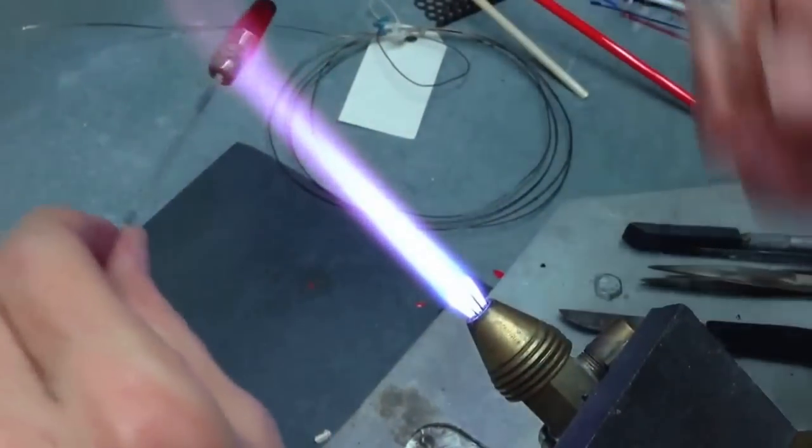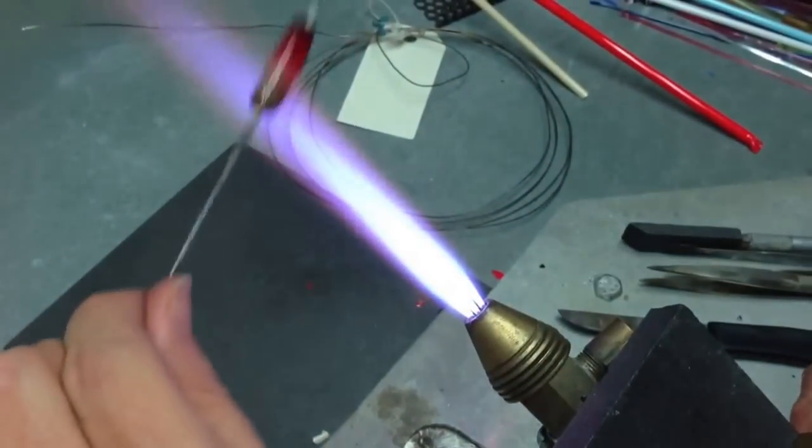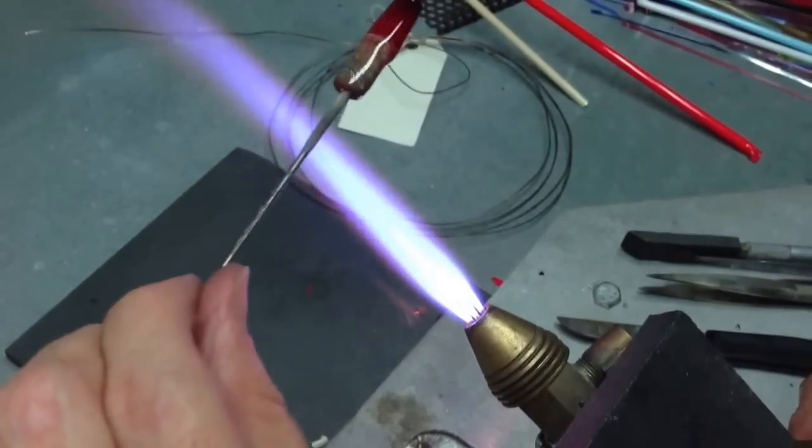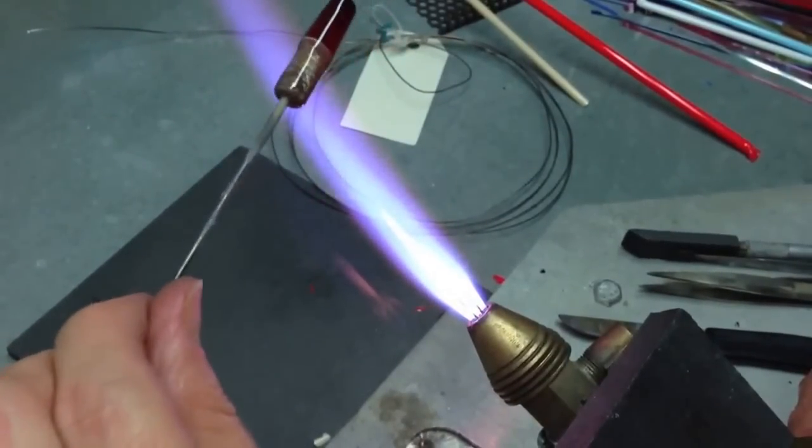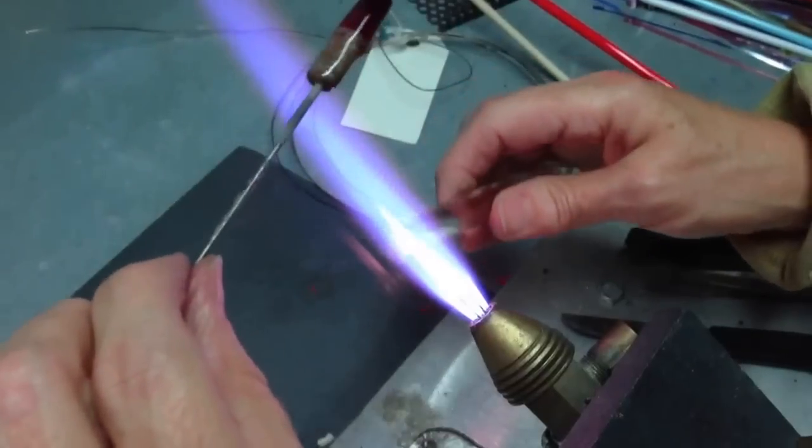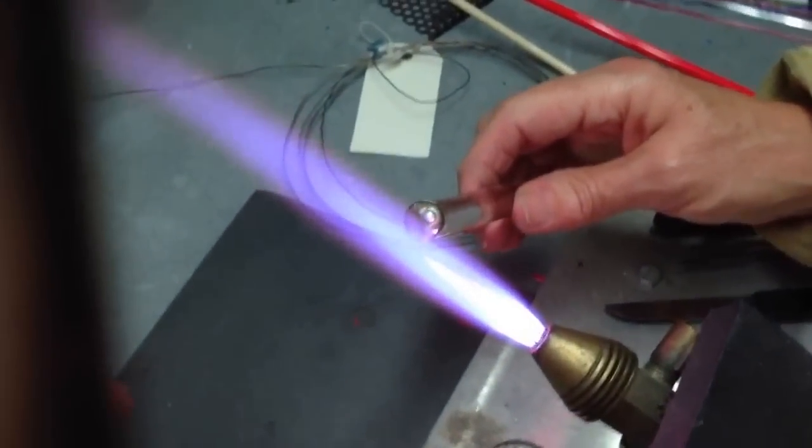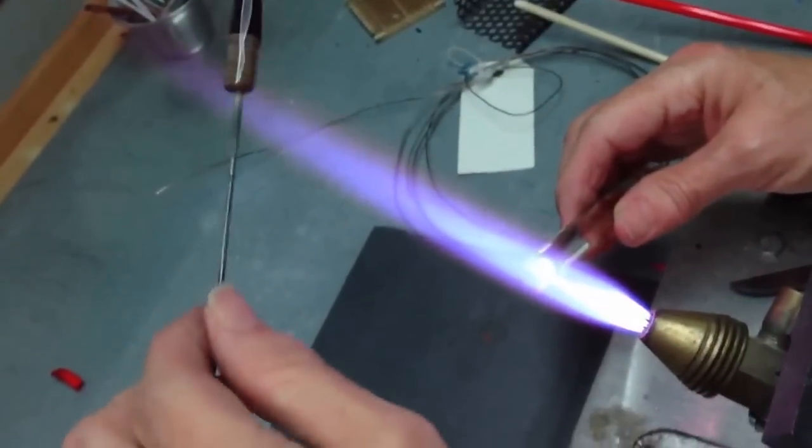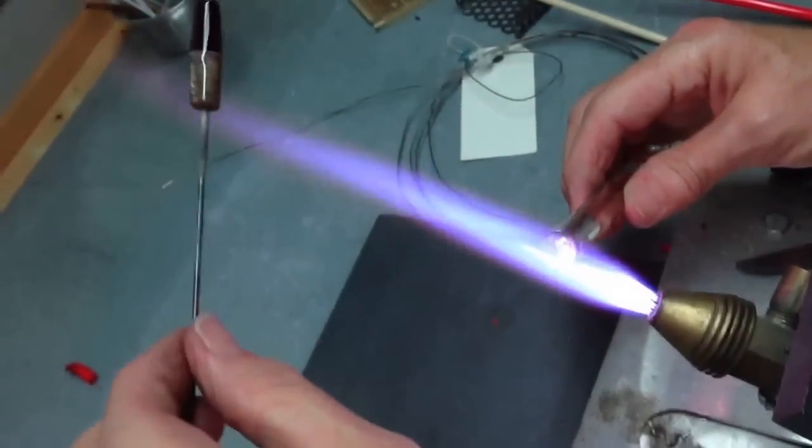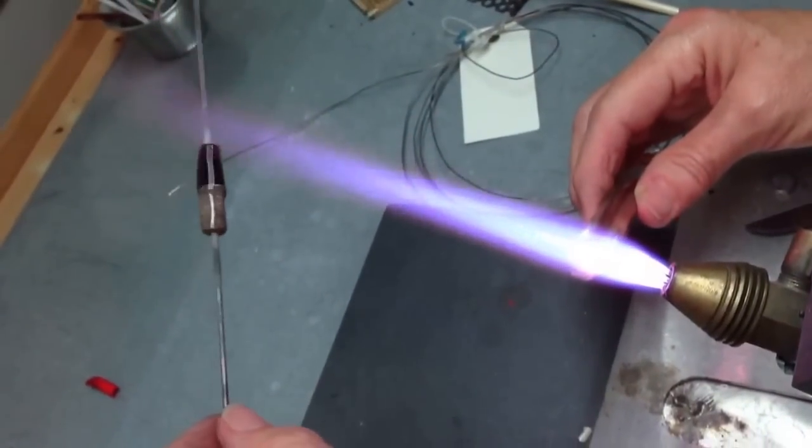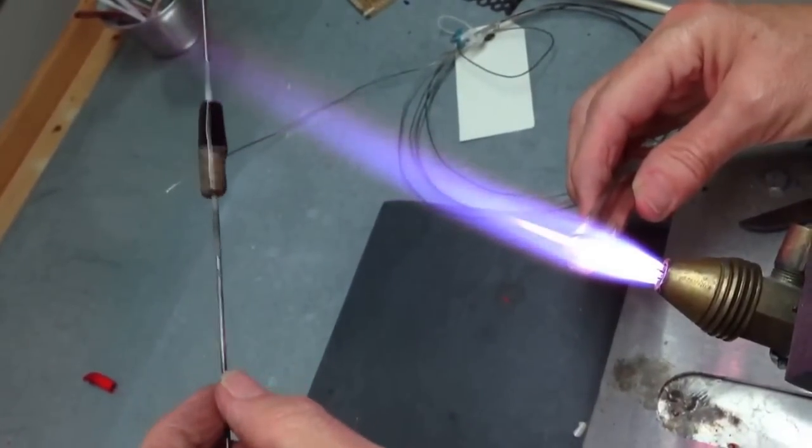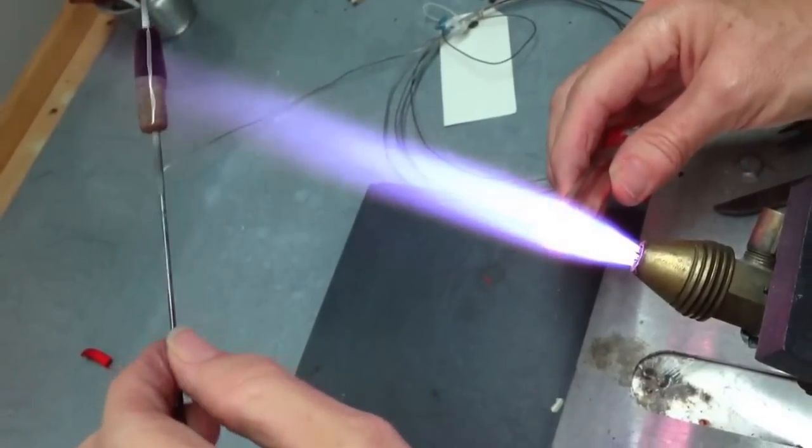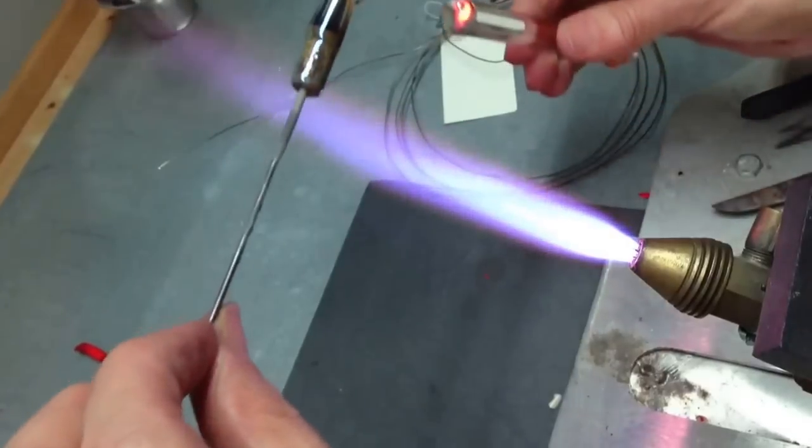We're going to fume again so we're making it more propane in the flame, about an inch and a half. Make sure your bead isn't molten or anything like that. You just want it fairly warm but not glowing. Then you stick that silver underneath and slowly into the flame until you see it fuming. And there it goes.